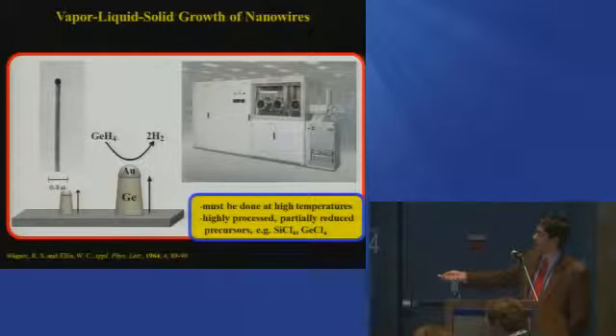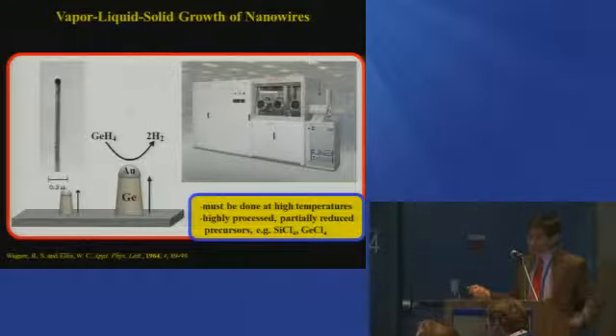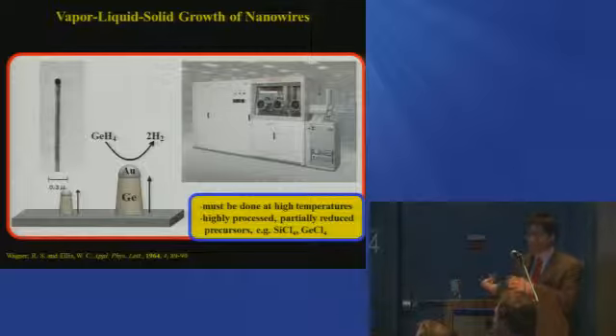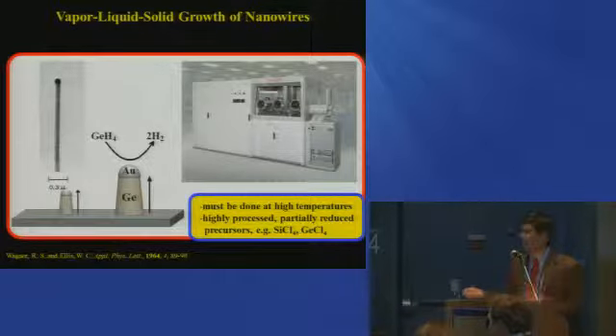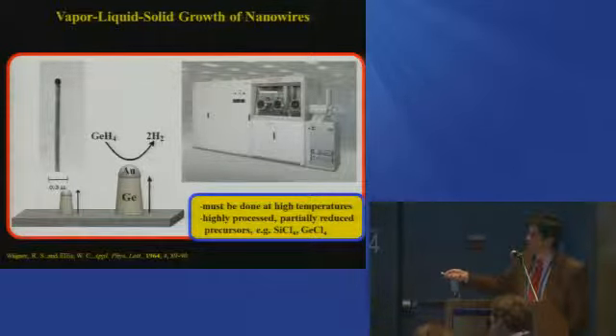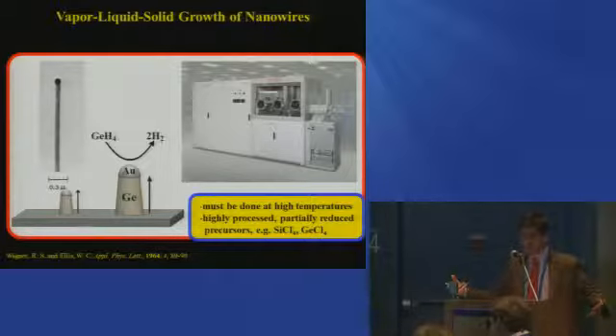People like to make nanowires, crystalline germanium nanowires, for example, using processes and equipment that look like this, and through a process that's known as vapor-liquid-solid crystal growth, where the idea is that they would make a platform, dot it with a transition metal, stick it in a furnace at a really high temperature, expose it to some relatively nasty precursors that then decompose at this hot liquid metal catalyst and then precipitate out a one-dimensional crystal or a nanowire. The disadvantage with this process is that it's awfully high temperature and involves precursors that you have to spend a lot of energy to make.